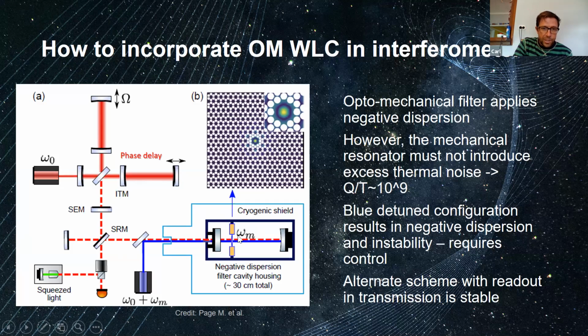And I guess the real challenge with these optomechanical filters is that you don't want to introduce thermal noise into your interferometer. Not introducing thermal noise into your interferometric signal means having an absolutely fantastic Q factor requirement, or having incredibly low thermal noise, and it means we need something in the order of where the Q factor divided by the temperature is something in the order of 10 to the 9.